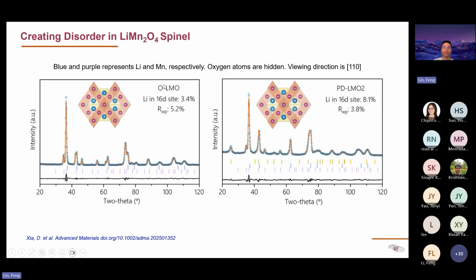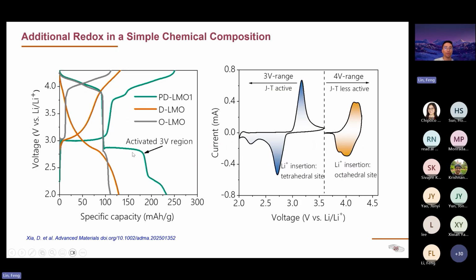And O here represents the original material. If you take the original material, you charge and discharge, this is your voltage profile, right? It has this capacity at the high voltage range, and then you get a capacity around 120 milliamp hour per gram. But if you perform mechanical milling of the material and create this partially disordered spinel material, you get an additional plateau that's present at around 3 volt.